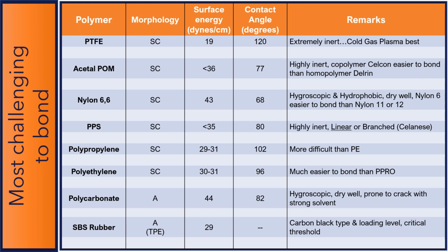PPS, polyphenylene sulfide, also a semi-crystalline, is also very highly chemically inert. What Sabrine has found is that the linear PPS offered by Celanese tends to be easier to bond to and actually have more robust bonds than the branched version. I do believe Celanese probably does offer both versions of this, but linear tends to be easier.